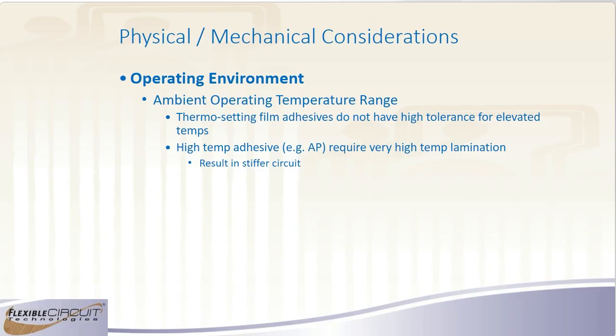However, if it's something where there's a lot of shock and vibration and it's seeing those elevated temperatures, you can start doing damage to the circuit because it will get much softer. And I've actually seen examples in the past where heavy components have been added to a flex circuit, and they've gone into an oven for a cure of some sort, and an operator pulls the flex circuit out by the flex itself, and as soon as those heavier pieces drop out of the oven, that shock can actually rip the flex circuit because it's gotten so soft during the baking cycle. So if you have thermosetting adhesives, like I said, which encompasses virtually everything out there, you have to be careful on what you're going to be running at for your ambient temperatures.